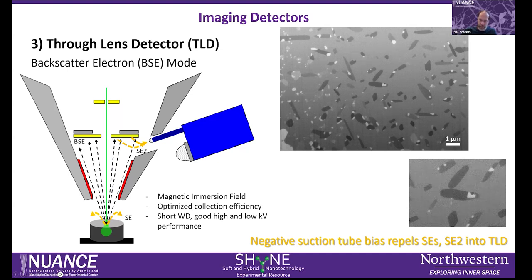And so you can basically get the backscatter image where now we have more chemical contrast, so higher average atomic number regions are showing up brighter. And what you can also see is that the curtaining effect is much less visible in this image.